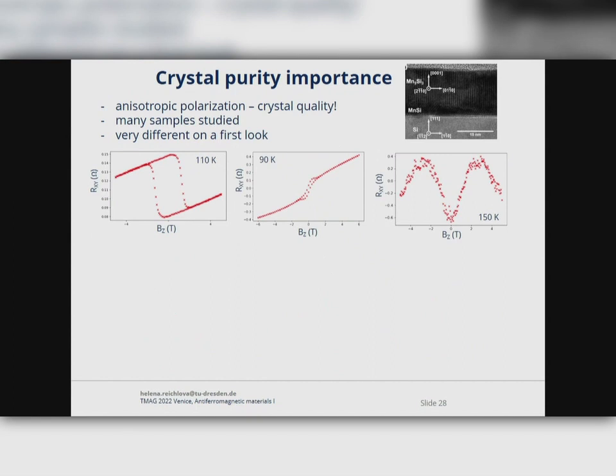So I told you that the crystal purity is very important because this effect relies on our non-magnetic environment. We also confirmed this experimentally: as during any growth optimization, we have samples of various quality. And you see here, when we measure different samples, these are the raw data as we really measure them in our cryostats.